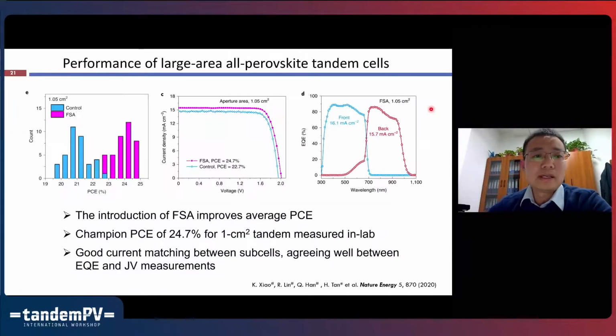And using those strategies, we can further increase the efficiency of the larger area tandem devices. The control device is less than 23%, and for the best tandem devices measured in lab, the efficiency is almost 25%. At the moment, we can even go beyond 25% for 1 centimeter square devices. And from EQE, we can also see that the current matching condition is quite good between the two subcells.